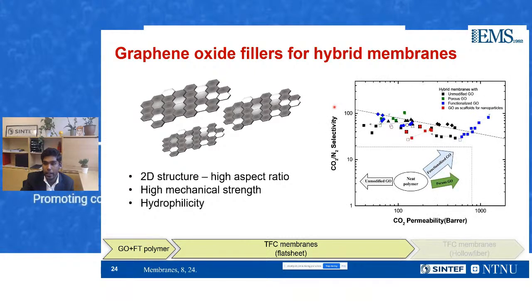We did a small review of the work done by so many people on graphene oxide, and we found that when you add graphene oxide to a system of polymers, it can move you in different directions with respect to the Robeson upper bound. The reason is the properties of both the polymer and the graphene oxide that we are adding into the system. One general trend we found is that graphene oxide on its own is a barrier material, so you eventually reduce the CO2 permeability. You may or may not increase the selectivity.